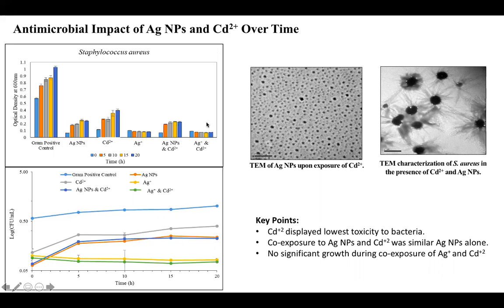However, upon co-exposure, we can see that cadmium and silver nanoparticles were still similar to silver nanoparticles alone, and cadmium and silver ions also did the same thing, following the behavior of silver ions alone. So it tells us that even though the cadmium is there, something is limiting the availability of that cadmium to those bacterial strains.